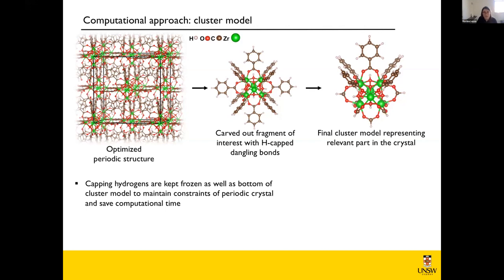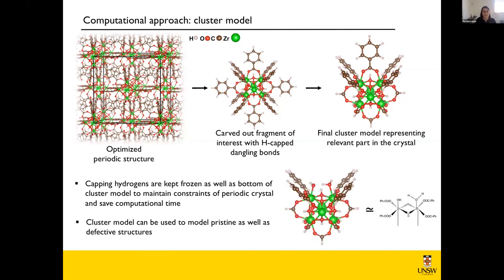And then once we have this nice model, we can actually play with it, replace the BDC with water to simulate, for instance, a very commonly found defect when water is around in UiO-66. And in the following slides, I'll just represent this defect site in a much simpler way for convenience.